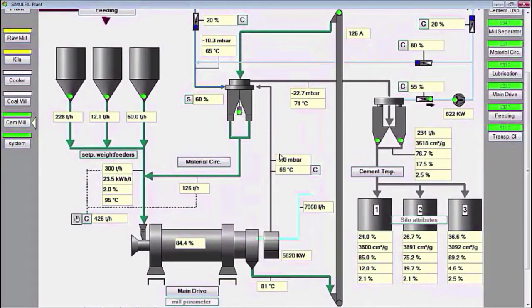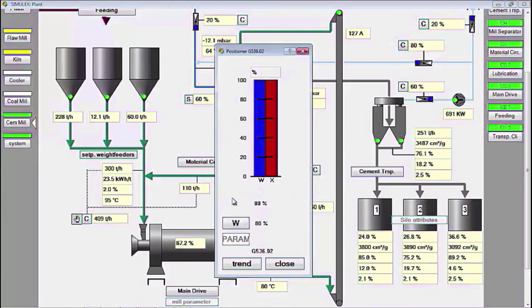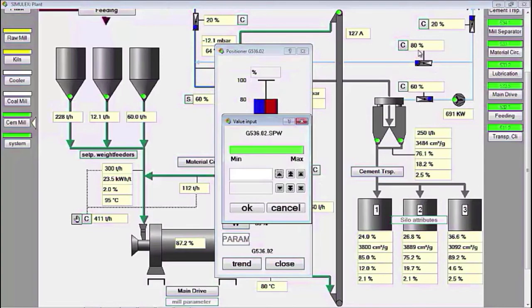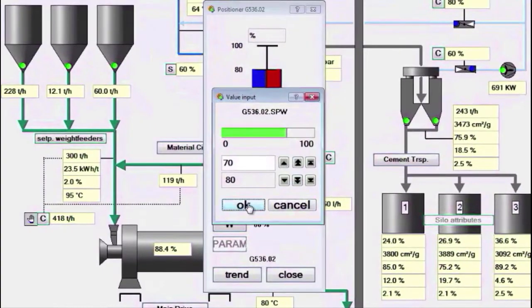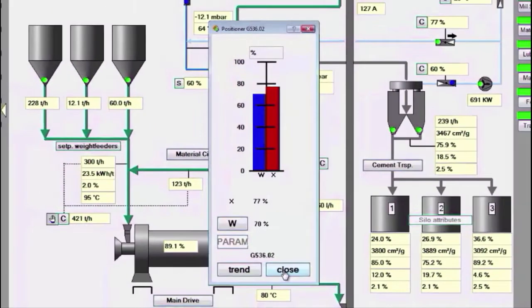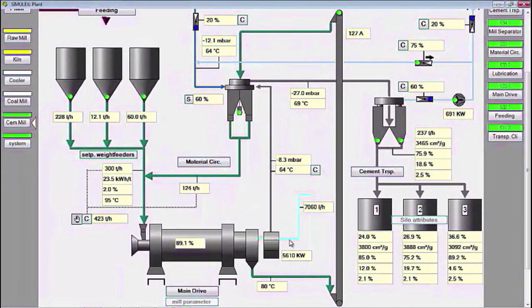The mill outlet draft is already minus 8 millibars. We can increase the draft at the outlet of this mill by reducing the circulation damper opening, which was previously opened by 80%, we lower it to 70%. And we expect this mill outlet draft to be around minus 11 millibars.